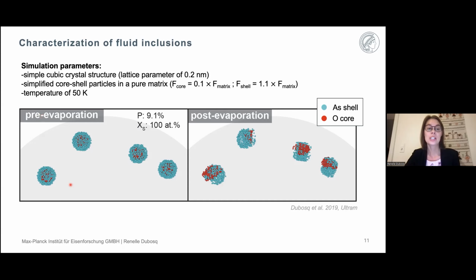For these simulations, we varied the size, or the ratio of the diameter of each of the fluid inclusions, relative to the curvature or apex of the sample. By varying the size of the fluid inclusions as well as the compositions of the shells, we were able to have a total of 6 simulations. And each of these 6 simulations led to a very similar post-evaporation morphology, as you can see here.